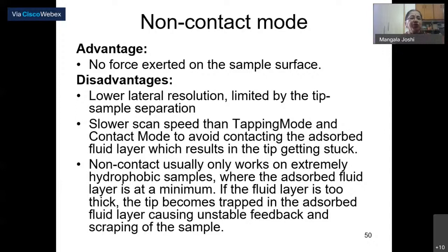In non-contact modes, no force is exerted on the sample surface because it never comes in touch with the surface. But the disadvantages are lower lateral resolution, limited by the tip sample separation, and slower scan speed. Then non-contact usually only works on extremely hydrophobic samples where the adsorbed fluid layer is at the minimum. And if the fluid layer is too thick, the tip becomes trapped in the adsorbed fluid layer, causing unstable feedback and scraping of the sample. So there are problems and advantages and disadvantages of all the three modes. Next.